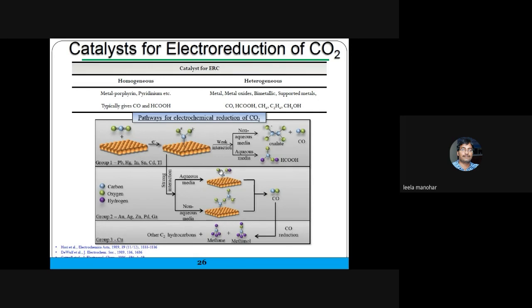When you have a stronger interaction in the aqueous and non-aqueous media, we have COOH, and again we have COO and CO minus. Again the intermediate carbon monoxide is getting on the copper, and CO is reduced to hydrocarbons like methane, ethylene, or some methanol, or some formic acid from using the copper. Mainly the hydrocarbons we're getting on the copper. There is a separate review on the electrochemical reaction of carbon dioxide on the copper electrode itself, because copper gives the selective formation of hydrocarbons with a very good Faradaic efficiency.